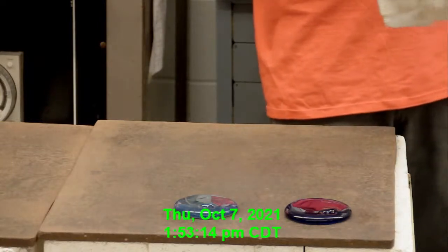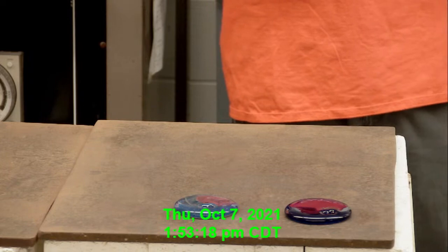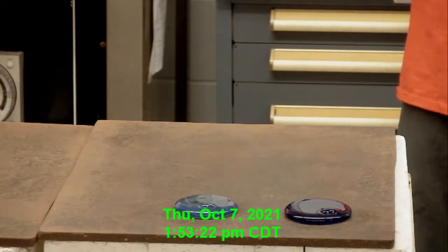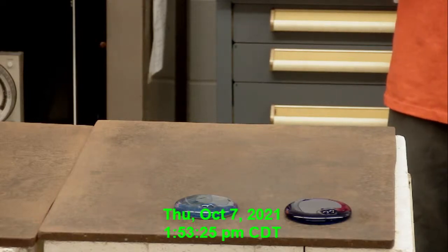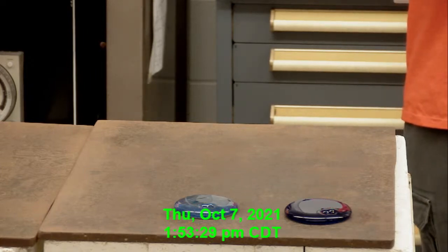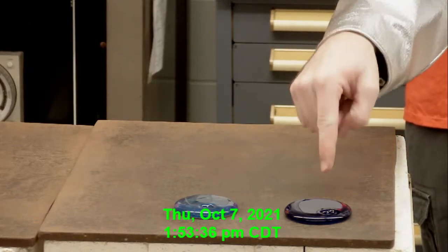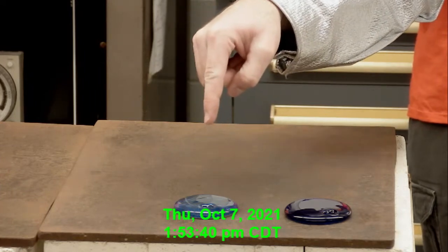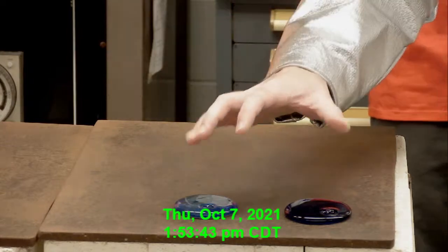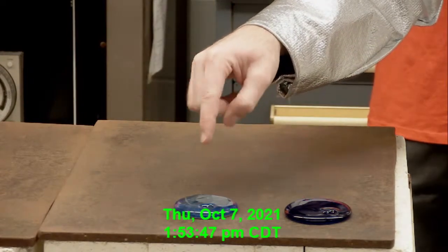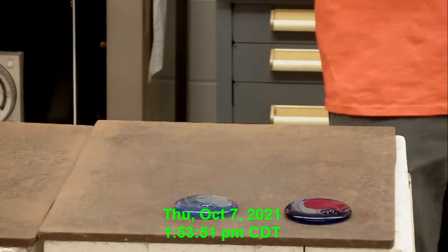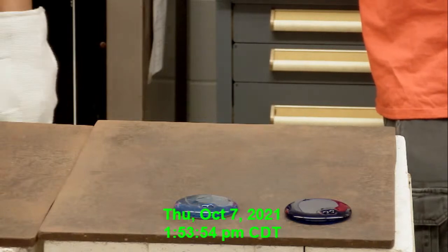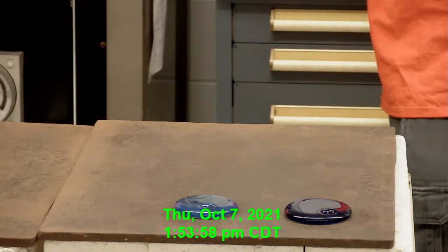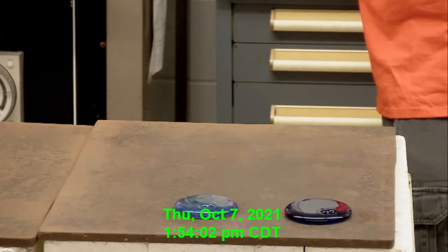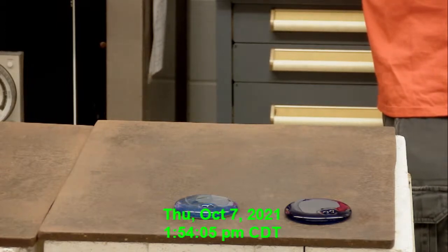Okay, so this is cobalt glass, but I think the loading might be different than what's listed. So let me just verify that. This says 0.02, and the previous one says 0.02. So I think it might be down by another decimal. I think it might be 0.02 and 0.002. Because this looks typical for 0.02, this looks like it's about a tenth less. So I think there might be a discrepancy on the record, but I think we can figure it out. It does look a lot lighter. So, no big deal, just trying to sort things out as we go.